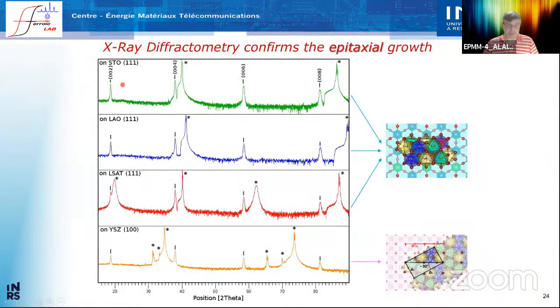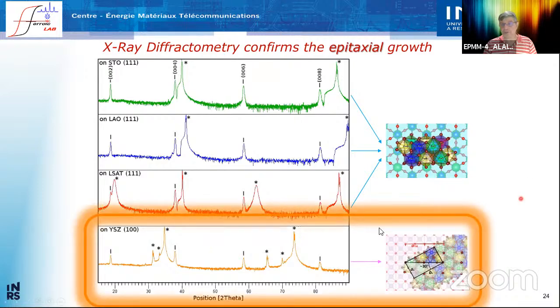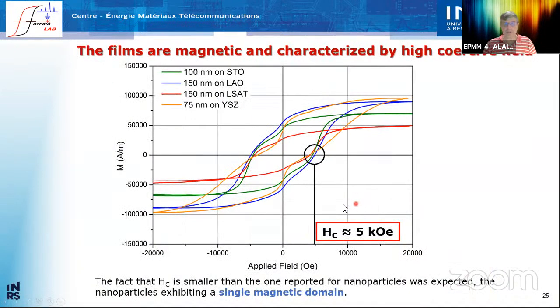As you can see, they are epitaxial. So along the c-axis, they are perfectly epitaxial. But along the in-plane, of course, you have this very complex epitaxial relationship. Well, that's a magnetic curve, and the magnetic coercive field is actually not exactly as large. You remember it was 5 kilo-oersted.